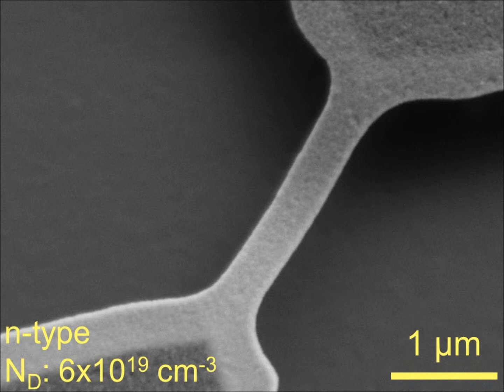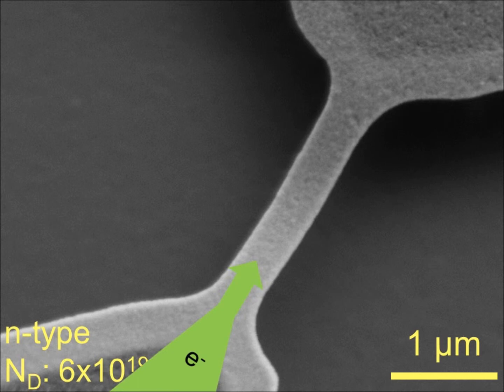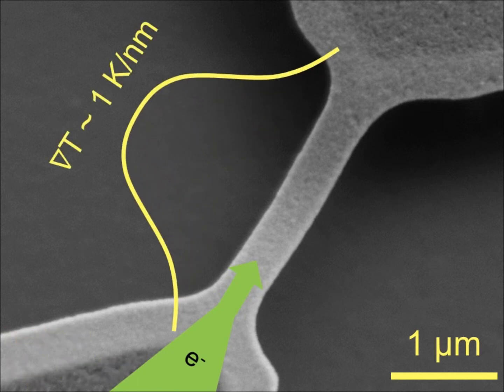We have observed very strong heat transfer by charge carriers, also known as thermoelectric effects. We started with nanocrystalline silicon microwires with a high doping density. Due to the low resistive nature of the wires, a large electrical current is forced through when the wires are biased with an electrical signal. This leads to a rise in wire temperature and forms a temperature profile due to self-heating, also known as Joule heating.